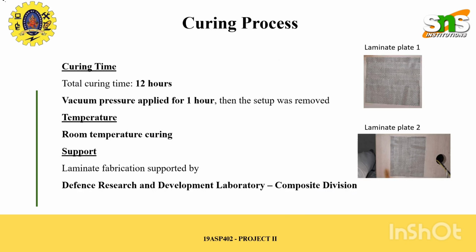After fabrication, the laminate undergoes a curing process at room temperature for about 12 hours. Vacuum pressure is maintained for the first hour and then removed. Proper curing is essential to achieve strong bonding between the fibers and the matrix. This process was supported by the Defense Research and Development Laboratory, ensuring reliability and quality in the fabrication process.